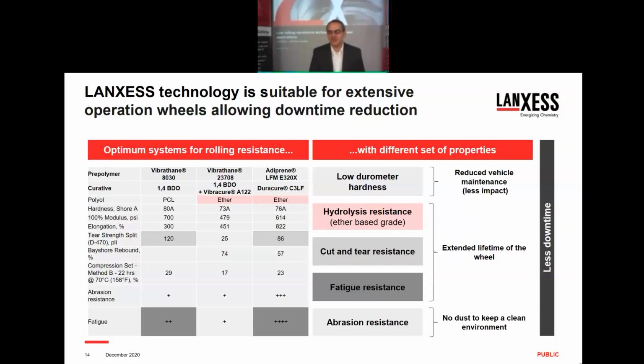When you move to the center one, that's the conventional ether. And what you'll notice is about midway down on that chart, you'll see the tear strength. On the left, the 8030 was 120 PLI, pounds per linear inch. The center, that 23708, drops significantly down to 25. So you're really giving up that tear strength. And again, the fatigue goes down with that. But you gain that hydrolysis resistance.